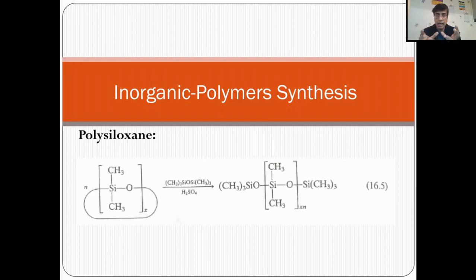So we have polysiloxane synthesis, and then we notice that the molar mass, I mean the viscosity of the solution, is not increasing. Why not? Because after the trimer and tetramer formation, a cyclic compound starts forming. That is why all the monomer is consumed, but molecular weight does not increase. This is the problem of this technique, but no worries, because after that we isolate and do the distillation. Unreacted silanol will be distilled out, and all the cyclic compounds which have a higher molecular weight will settle down, and then we add sulfuric acid into that solution, and this sulfuric acid does the ring opening polymerization.